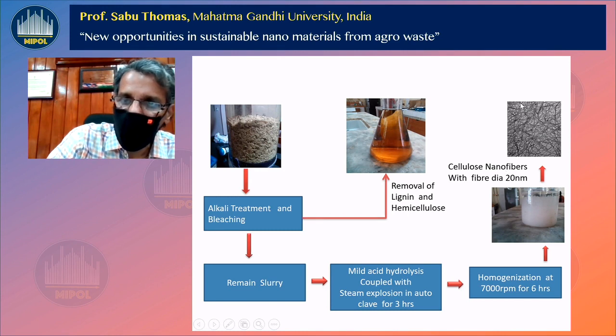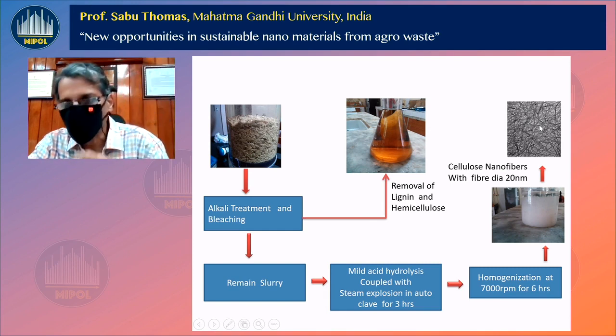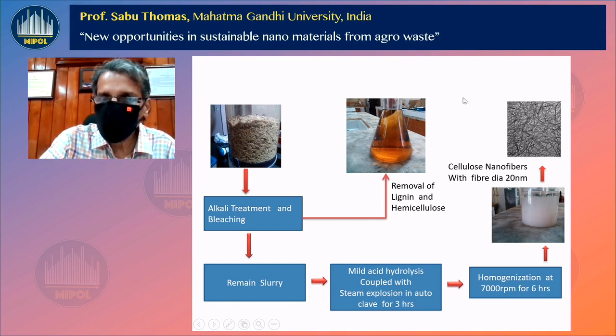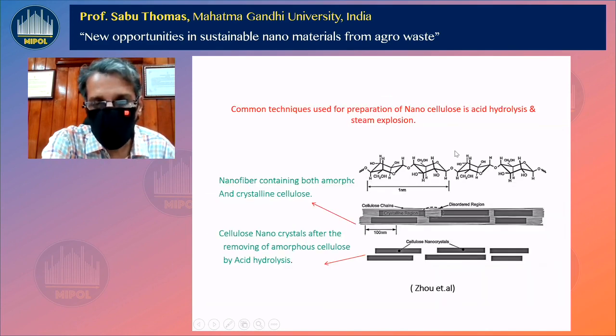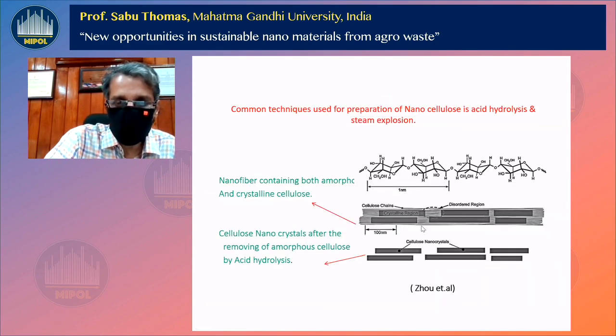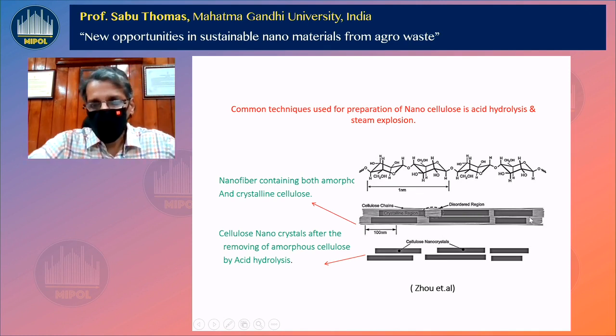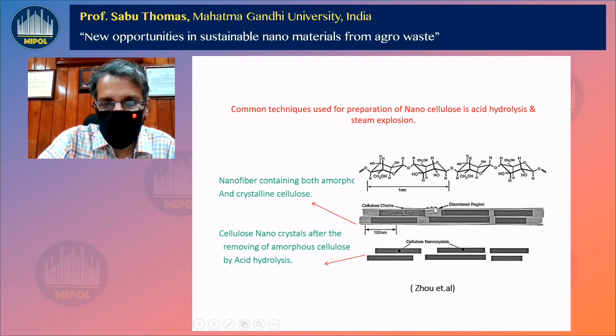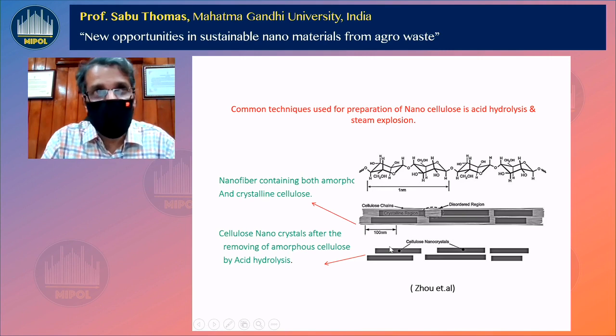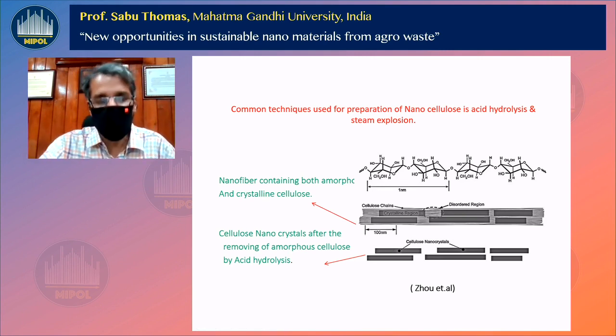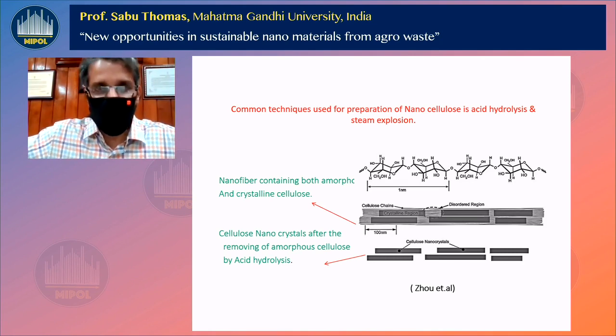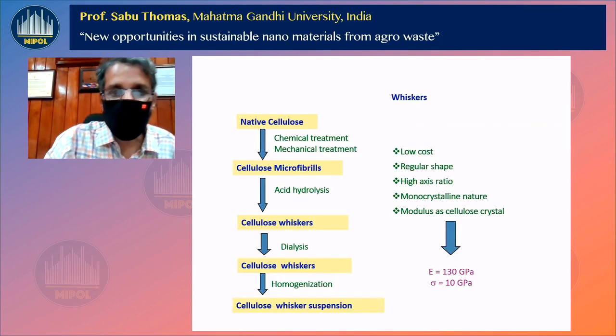Dear friends, eventually, you know what you get? You get beautiful nanofibers. If you use strong acid, you get nanocrystals. You can differentiate them from this picture. This is a long nanofiber, where crystalline and amorphous phases coexist. If you remove the amorphous entities, what you get is short nanocrystals. So you can make either long nanofibers or short nanocrystals.